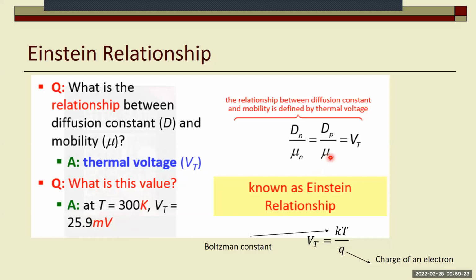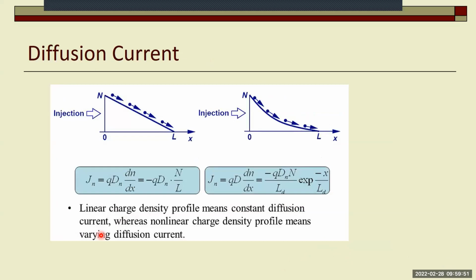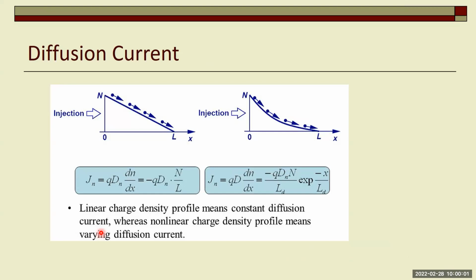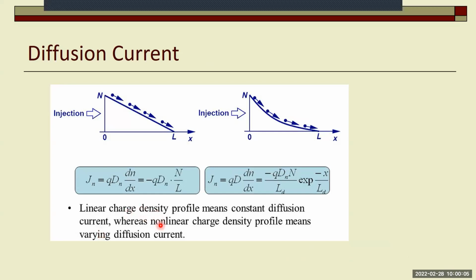Anyway, so this Einstein relationship, when you divide the diffusion constant by the mobility of that specific charge carrier, either hole or electron, is constant. And at room temperature, it's a function of Boltzmann constant, absolute temperature divided by the charge. And that's 25.9 millivolts. So the diffusion current was from the higher concentration to lower concentration, right? And linear charge density profile means constant diffusion current. Nonlinear charge density profile means varying diffusion current, like seen in these examples.